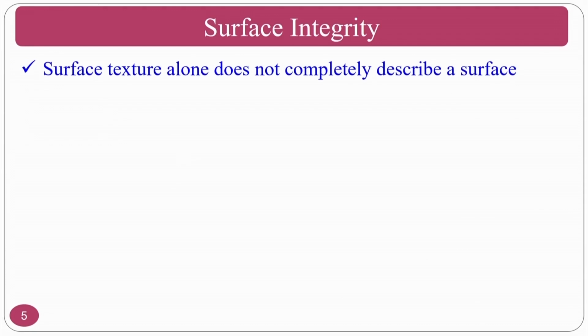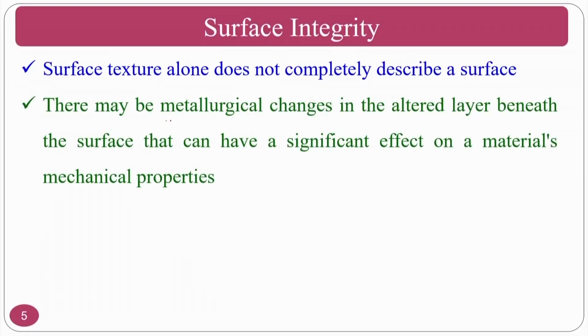Surface texture alone does not completely describe the surface, because the surface will have roughness, chips, that is burrs, burnt regions, and many other things, since a lot of kinetic and mechanical energy is involved in a mechanical system. There may be metallurgical changes in the altered layer beneath the surface that can have a significant effect on the mechanical properties. Assume the surface is very smooth, but burnt. When you put this component in a practical application, the metallurgical changes will lead to failure of the component. Even though the surface roughness is very good, the component fails because of crack formation during practical application.